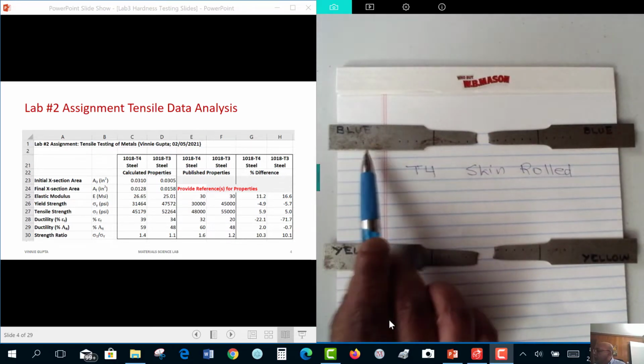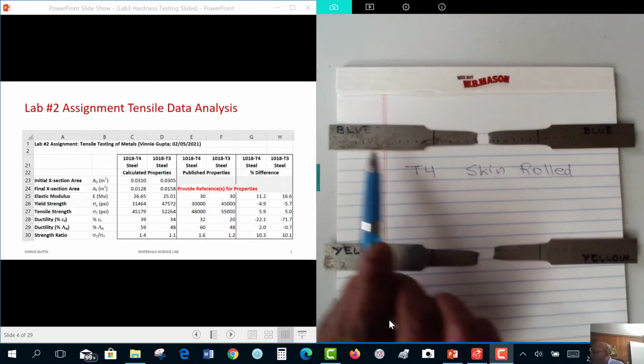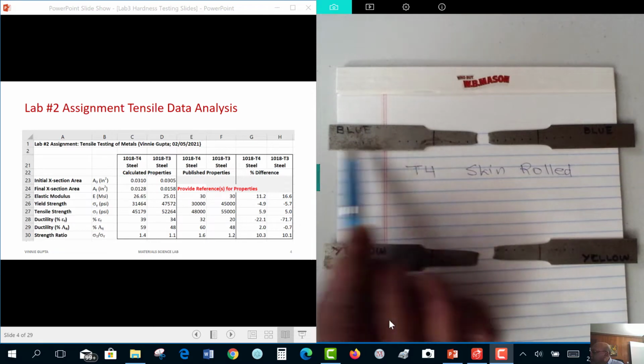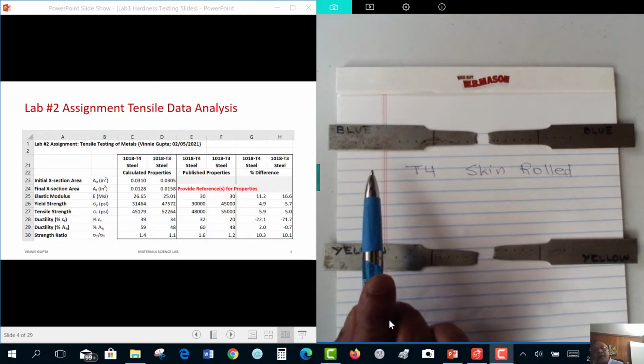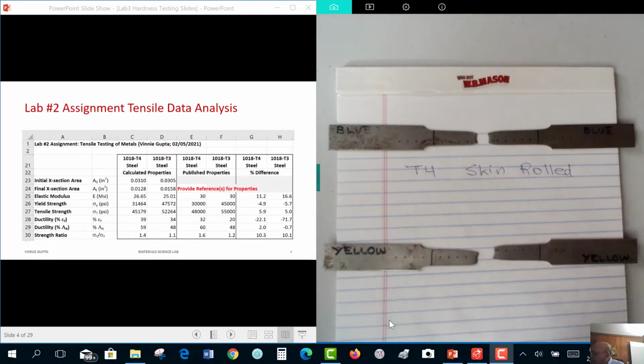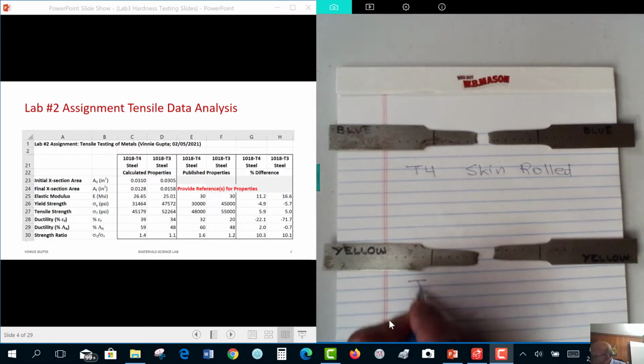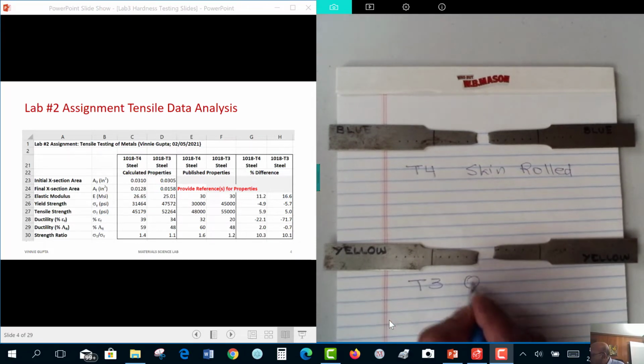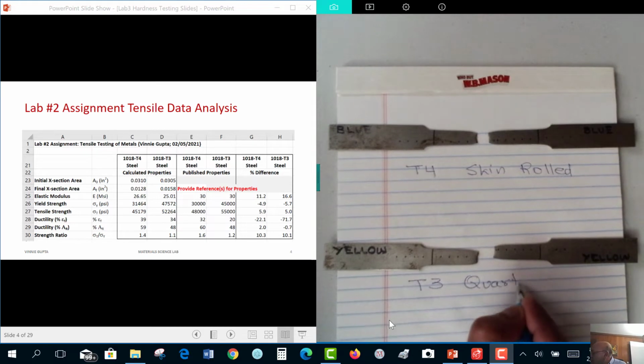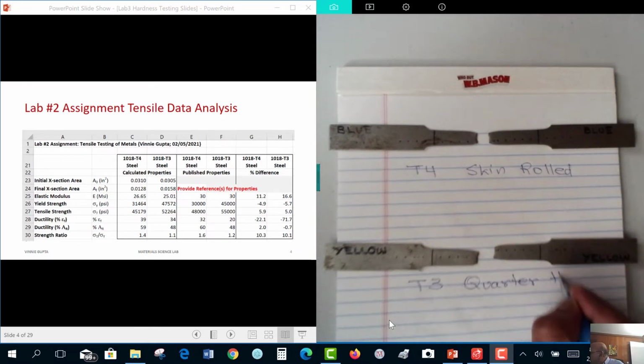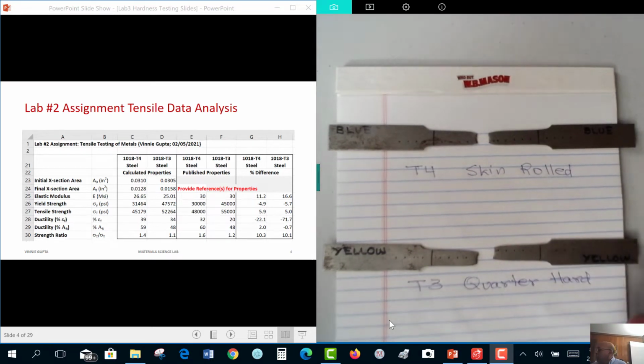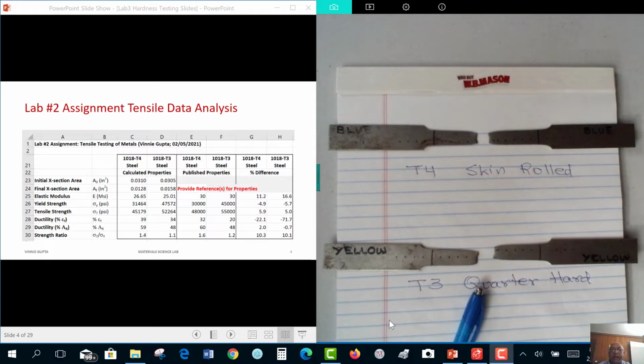That means during rolling, we applied small force so that only the skin or the surface became harder due to plastic deformation. Whereas in this T3, we applied a larger force so that it became quarter hard. If we apply still larger force, we can make it half hard. Even larger force, it'll become full hard, the highest hardness that we can get.